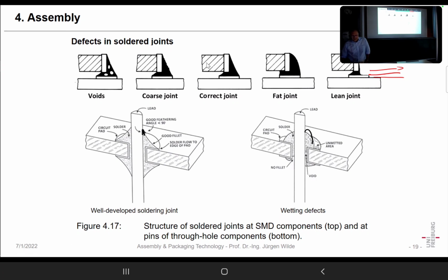And from that, for instance, some people look at the solder joint and they can tell you what the content of which impurity is. They can tell you it is 100 ppm of iron or so just from how it looks. Very interesting, but it's not so important anymore because we go for reflow soldering mainly now.